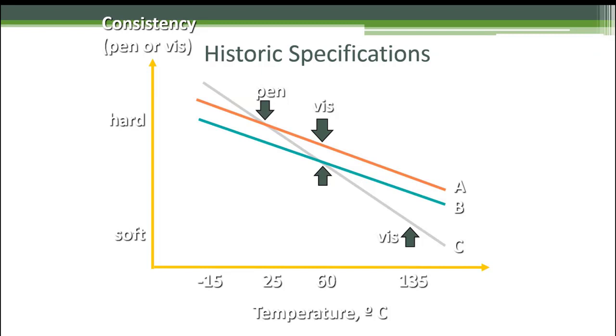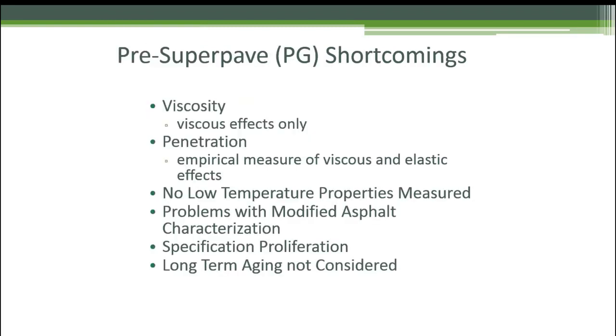So with a combination of PG binder, Superpave, and better control of the mix, better design of the mix, we can get both. And that was the kind of initiative of PG binders, performance graded binders. Depending on which spec we used, it was a single point measure. Unfortunately, in both of those, none of them measured a low temperature property, which can be the biggest killer of pavements in the Dakotas, right?